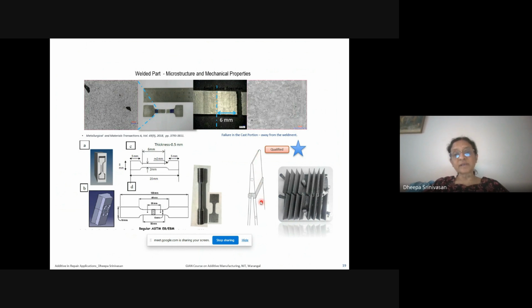So we took this and developed a technique to build this additively manufactured coupon on the repaired part, which is the vane. And very happy that the failure did not take place exactly at the joint. The failure was actually very much inside the cast FSX414, as you can see here. This is the distance, about 6 millimeter also. This is the distance where the safe zone is, the additively manufactured coupon zone of cobalt chromium.